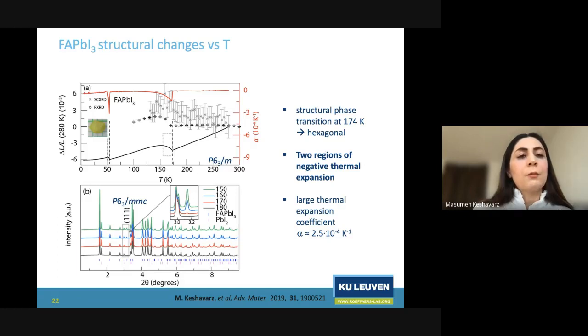Now let's change methylammonium, the A group, to formamidinium and see how that changes the structure of the crystals. By changing just MA to FA, which has a slightly larger ionic radius, we see that the formamidinium lead iodide crystal is not perovskite at room temperature anymore. If you heat it to 120 Celsius, it becomes black and perovskite, but at room temperature it's not conductive, and it's not in a perovskite phase. So we did the thermal expansion measurements nevertheless, and with help from our colleagues from Denmark, who did high-resolution X-ray diffraction measurements, we could identify the phases of the material at each temperature range.